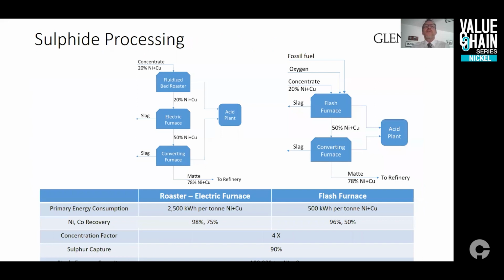This slide illustrates the two main processing routes for smelting nickel sulfide concentrate. Nickel sulfide concentrate typically contains copper, but the nickel to copper ratio really doesn't affect the process. In the roaster electric furnace process, concentrate is roasted in a fluidized bed roaster to remove a portion of the sulfur and oxidize a portion of the iron. All of the energy comes from the concentrate itself, so no additional fuel is needed. We call this an autogenous process.